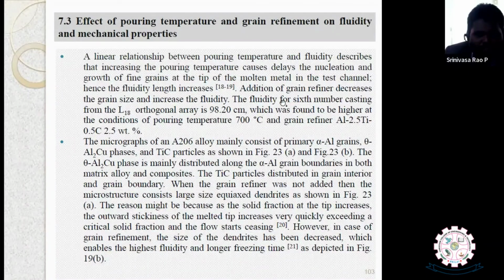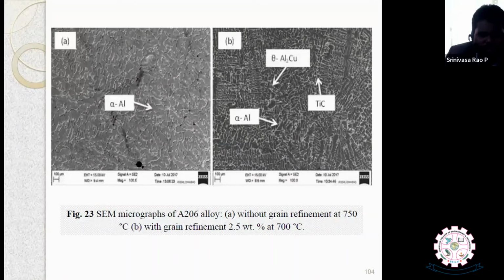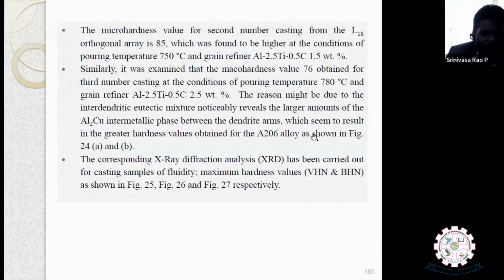And also addition of the grain refiner actually sharpens the grain size and makes the grain globular. If the grain becomes globular, that means equiaxed, then naturally the fluidity will be increased, and the quality of the casting will be improved. That is what we observed in the sixth experiment, where we found that the fluidity length is 98.20. The corresponding pouring temperature is 700 degrees centigrade, and the grain refiner is 2.5%. We carried out the microstructure also for the optimized condition, and we got this type of microstructure. If you see the microhardness value for the second casting from the L18 orthogonal array, it is 85.